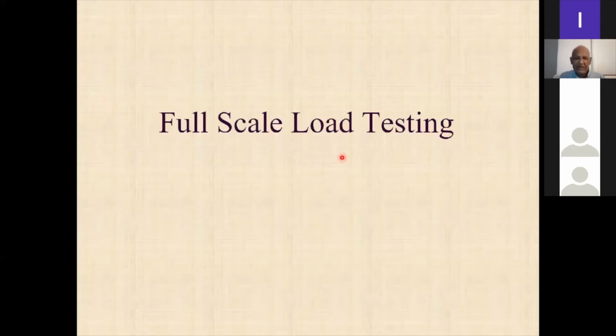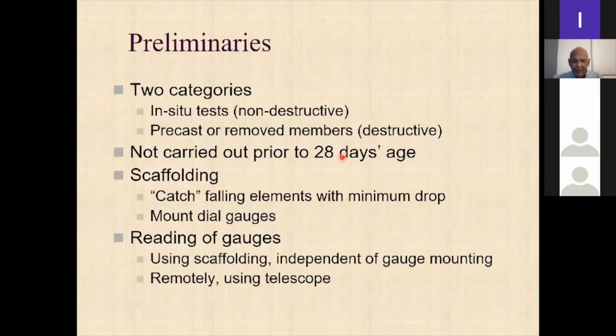Full-scale load testing, you can have either in situ non-destructive tests, or if you can actually remove a member or precast members, you can test it to destruction. You should not carry it out before 28 days of age. You must have scaffolding so that you can mount dial gauges, because the load testing is actually measuring load versus deflection, right? And also, if by some chance there is a failure, then the scaffolding should be able to catch the elements with a minimum drop, right? When you read these gauges, it is better if you read them remotely using a telescope in case there is some kind of unforeseen accident.